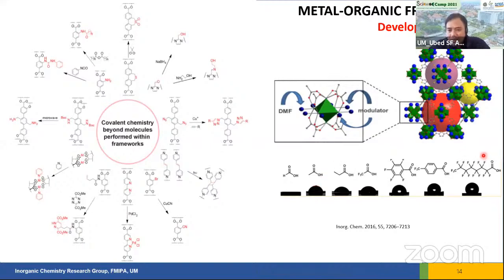But if we change the organic ligand to one with a lot of fluorine functional groups here, we can make this MOF into a hydrophobic MOF, meaning that they tend to repel the water. So we can modify our MOF to form a hydrophobic MOF or hydrophilic MOF by only changing the organic ligands. So this is a very beautiful strategy to make hydrophobic or hydrophilic metal organic frameworks.